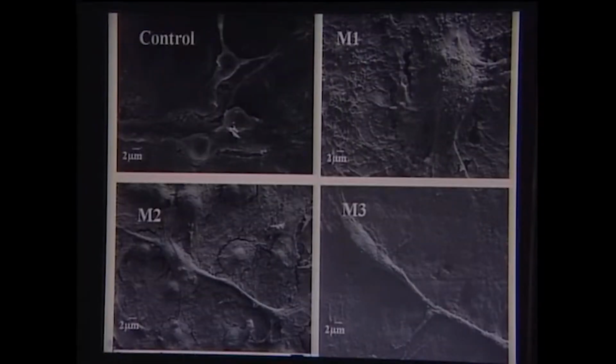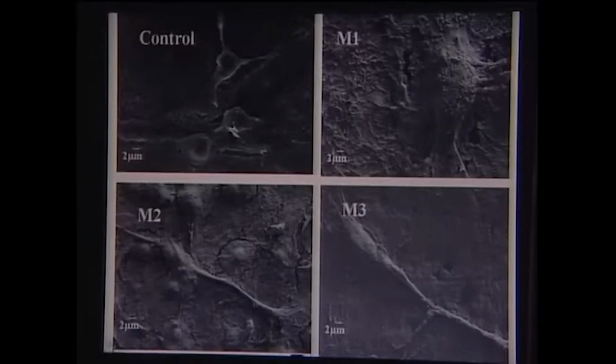Now, we have done in vitro cytocompatibility testing using SaOS2 cell lines. SaOS2 is a human osteosarcoma cell line, and these cells were cultured for 24 hours on these glass ceramic materials. You can see the filopodia extension of the cells, this is cell number 1, this is cell number 2, and that leads to cellular bridge formation. And also you can see long filopodia extension. So, that essentially indicates the cells are in a migratory condition.